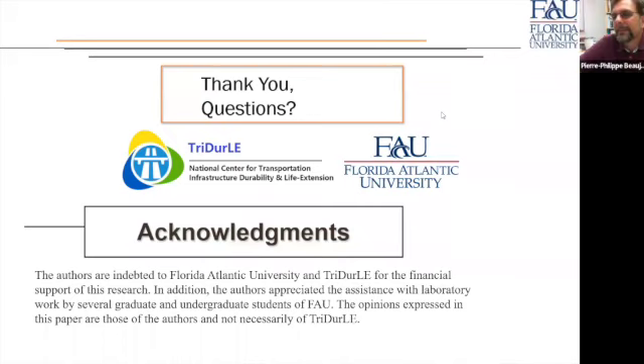Well, I'm going to answer another way. Spatial resolution is less relevant in the method I am using. The spatial resolution of the transducer I use is of the order of 9 millimeters, which is not very good. The best transducer you can use for work at higher frequency may give you a spatial resolution of the order of maybe 4 or 5 millimeters. But the model I use is detecting the crack based on a match in really the frequency domain of the response of the signal. So let me just go back a little bit on slide 19 very quickly.